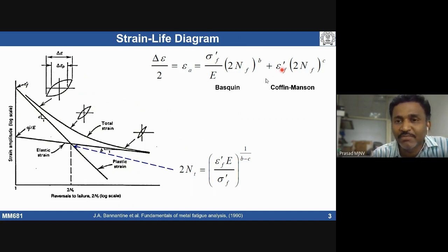People have expressed mathematical equations to describe high cycle fatigue and low cycle fatigue. High cycle fatigue can be described by using the Basquin equation, which relates stress amplitude or strain amplitude with respect to number of cycles to failure. Similarly, the Coffin-Manson equation expresses how the strain amplitude varies with the number of cycles to failure. One is for high cycle fatigue, the other for low cycle fatigue. If I want to know where the transition is going to happen, I have to equate these two terms. Then I can get where the transition from low cycle to high cycle fatigue takes place.